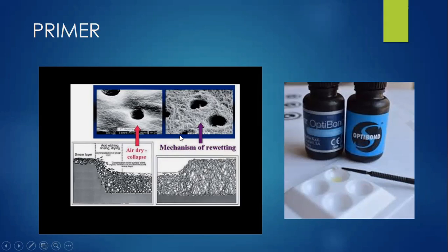HEMA is the most commonly incorporated in primers. It enhances dentin wettability, allows re-expansion of the collagen network, and improves the bonding capacity of adhesive resins. So when we dry, the dentin collapses. After we etch, rinse, and dry, there is a collapse of the collagen. We don't want collapsed collagen. For that, when we apply a primer which has HEMA, it leads to expansion of the collagen and creates nanometric spaces through which resin can infiltrate.